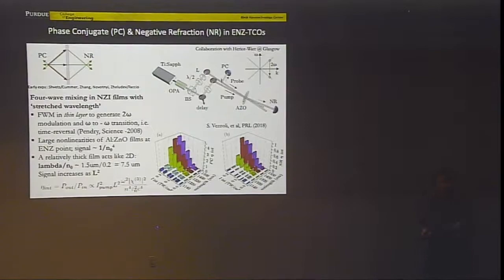It's a nonlinear process, interesting in many regards, and there was some experimental demonstration, but in all cases the efficiency demonstrated was below 0.1%. We took the same process, but we took this aluminum doped oxide, which Sasha makes, and we took it to the spectral range where the refractive index goes to 0, or is very small. And you could see that the efficiency for this process has the linear refractive index in the denominator to the power 4. In the previous case, it was the Kerr effect. This is a 4-wave mixing effect, and you have the refractive index going to the power 4. It should be dramatically enhanced.